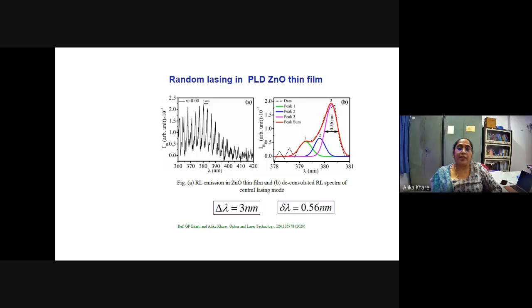We then enlarged one particular mode to find out the FWHM. The FWHM of this longitudinal mode was around 0.56 nanometers, which is quite narrow, and this again shows that laser action is coming out - this is a random laser.